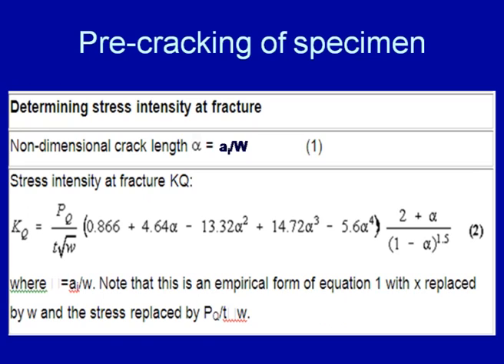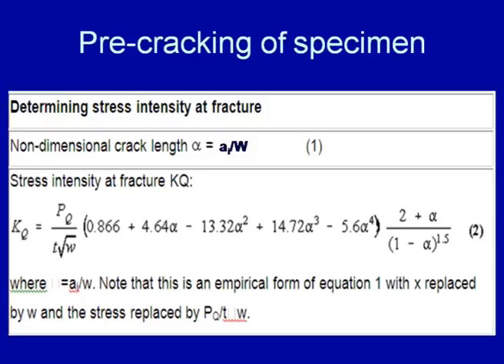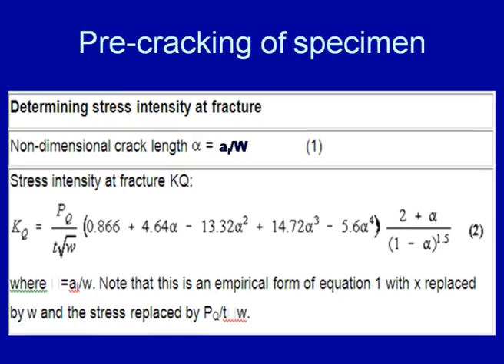This fracture toughness is calculated using this equation, where PQ corresponds to the maximum value of the load up to which the metal system has the linear relationship between the load and displacement. If you see here, the main parameters are T, the thickness, and W, which we have already defined. PQ is the maximum load up to which there is the linear relationship, and alpha is the ratio of A by W, the non-dimensional crack length.